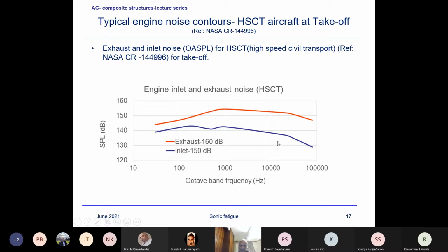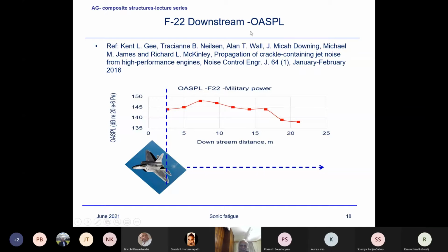Some of the slides here show typically the sound pressure level, SPL, with octave band frequency, because this can be converted to either octave band or 1/3 octave band, the response, sonic pressure loading versus frequency. And using this one can also analyze the response. So I just wrote some, and this is for a military aircraft like the F-22 downstream. Say here, the jet engine is there, and you can see for the F-22 how overall sound pressure levels vary as you move downstream from the jet. So it's a typical example.